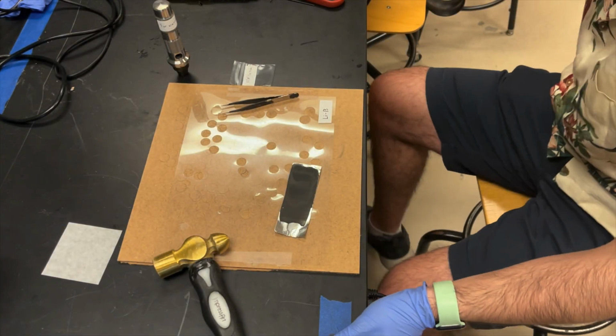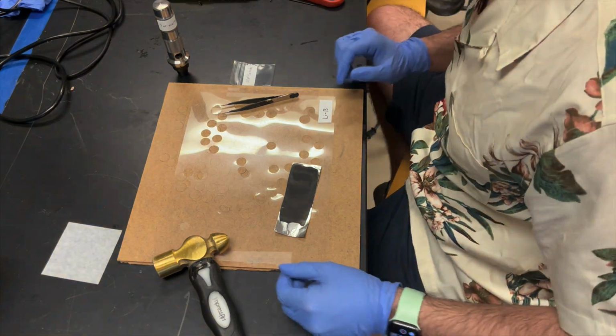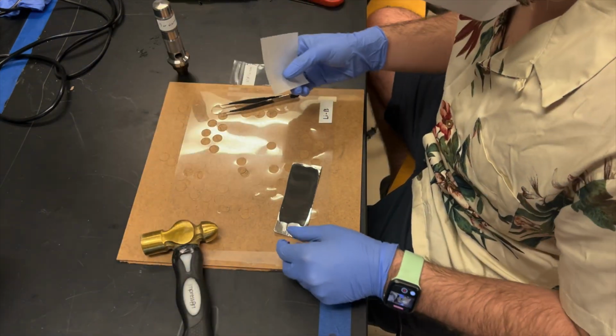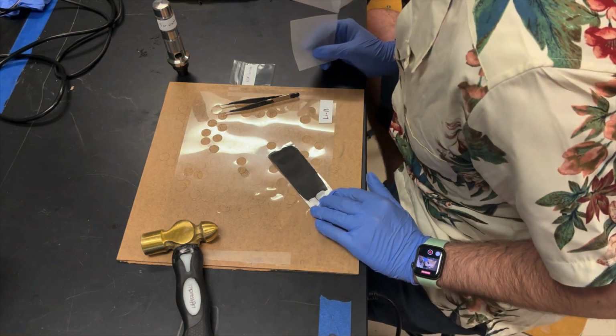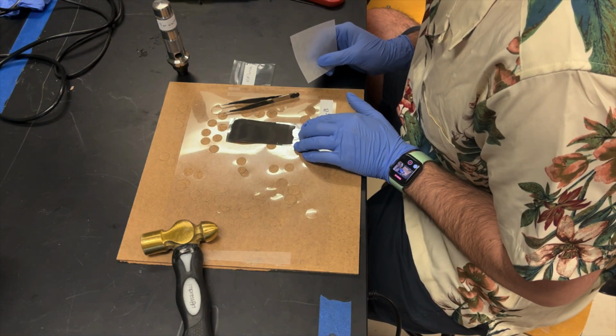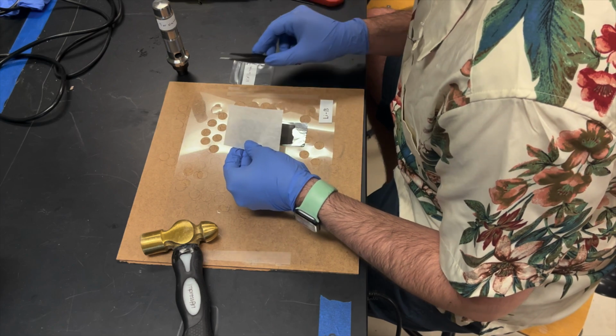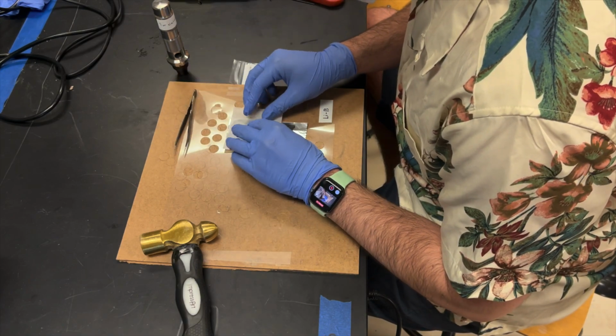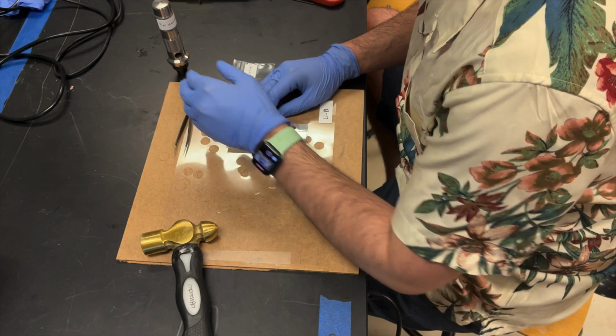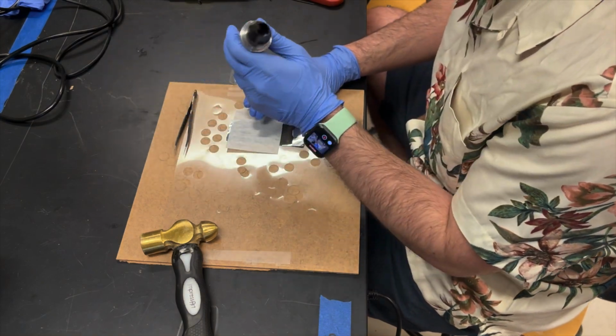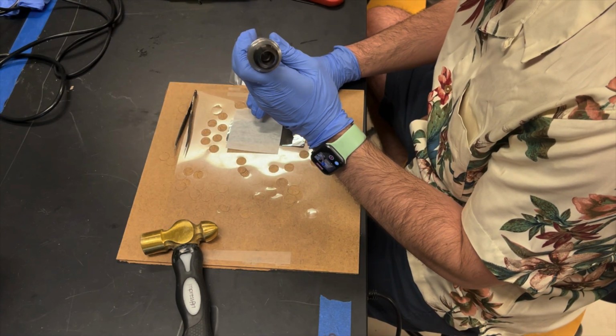For some devices, they may roll up their electrodes into a tube with a separator or dielectric between them. But in order for the electrodes to fit in our coin-type devices, we must punch them into discs. With a hammer and disc puncher, we will punch out these electrodes on a board with a sheet of plastic on top. For ease of use, I like to tape the plastic sheet to the board.